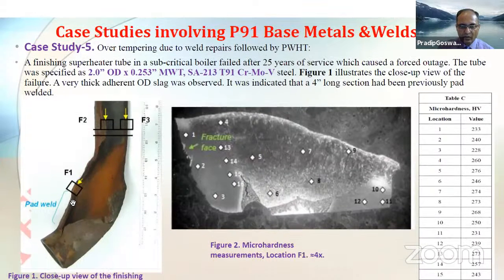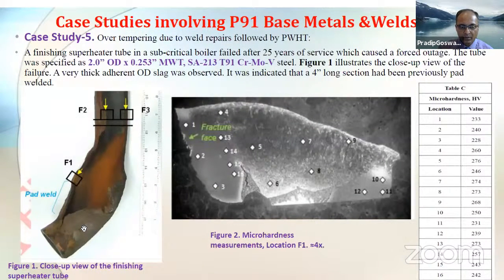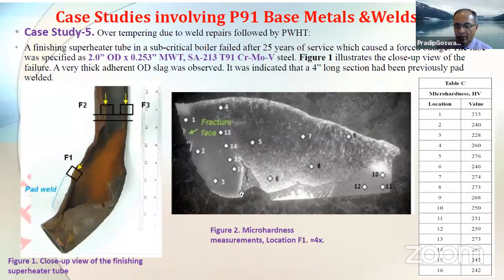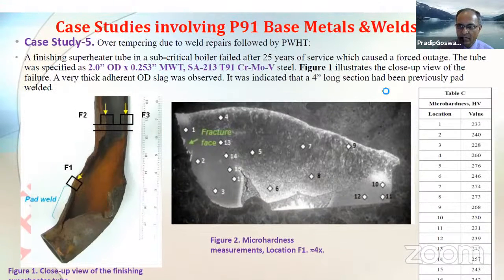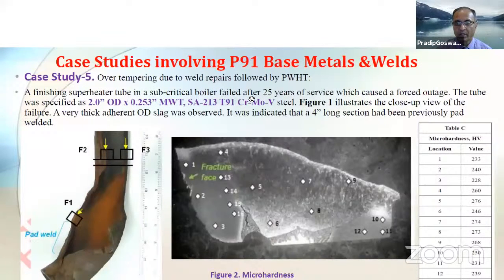And here, what is shown is the failure pattern, or the close-up view of the failed superheated tubes. And these are the hardness profiling, or the hardness readings taken at the various failed sections. So as you see here, at different locations, when you take the average hardness, the readings were, I would say, between 230 to 276 Vickers, which is typically nominal for this grade of steel after complete fabrication. But failures can happen, and in this case the failures happened after 25 years of service, which is fairly reasonable, I would say.